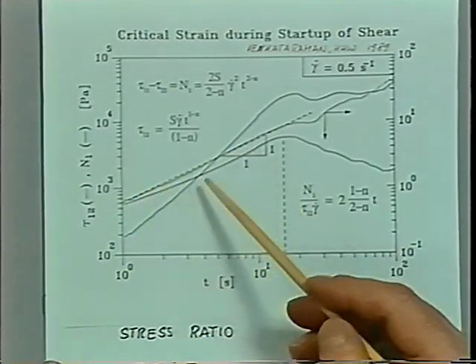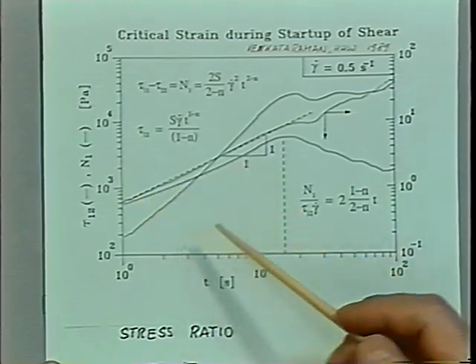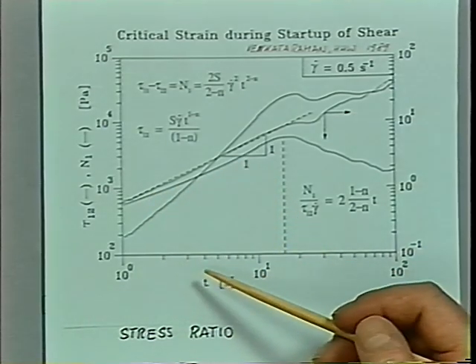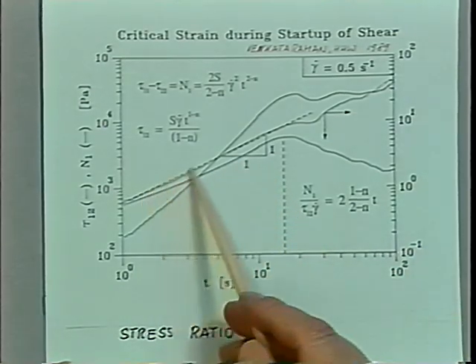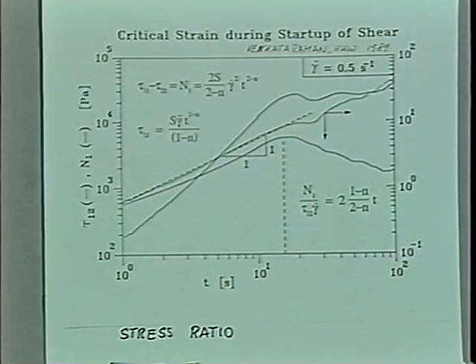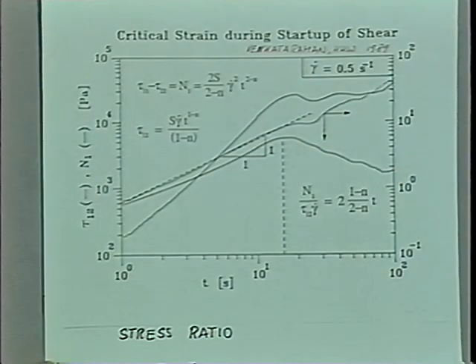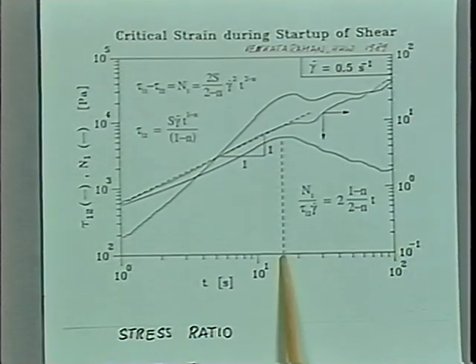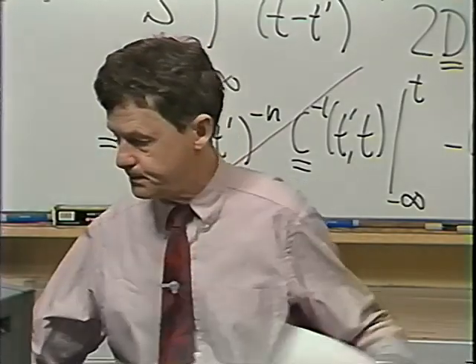Here, the data are not perfect. There's a little bit of curvature. He doesn't have a sample exactly at the gel point here, but the ratio is really very close to a function which is proportional to the time t. And at some strain, say a strain of 2, the material starts breaking and everything changes.